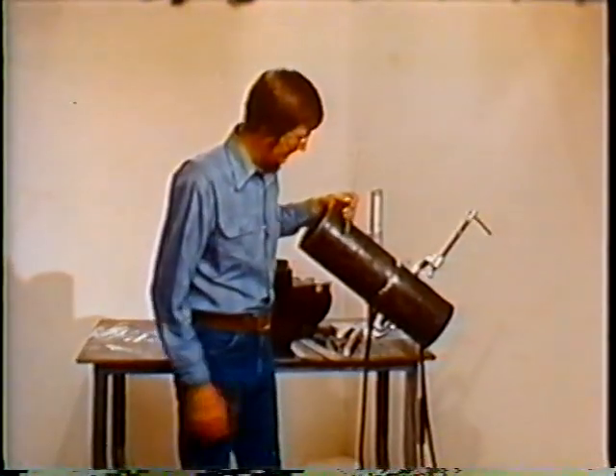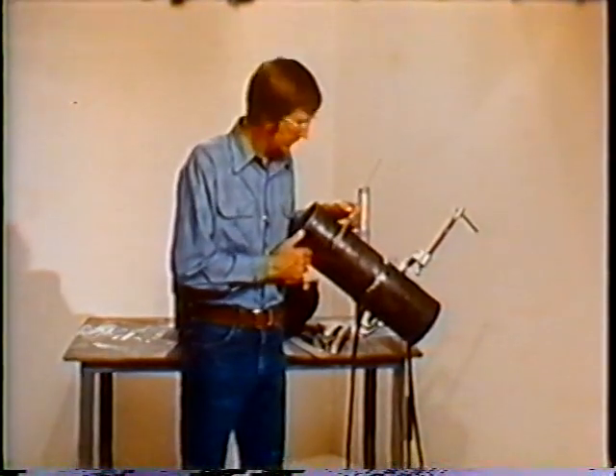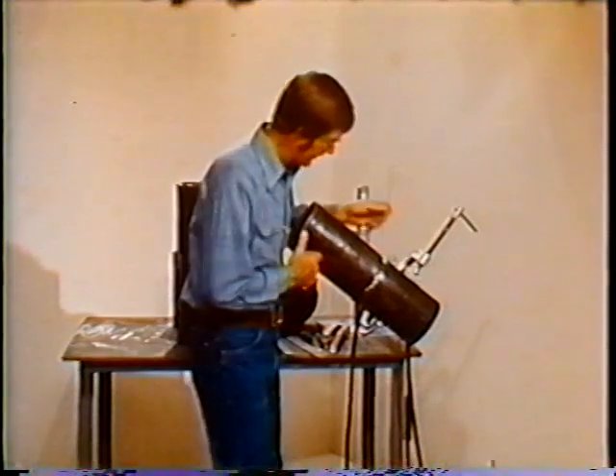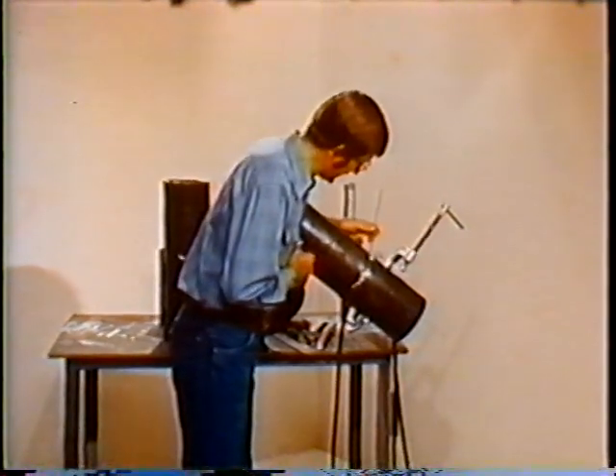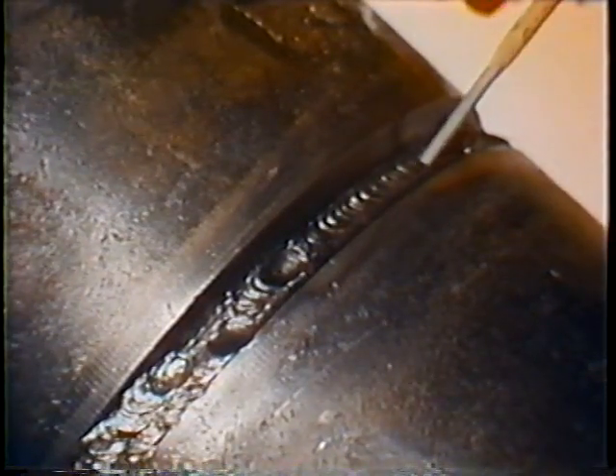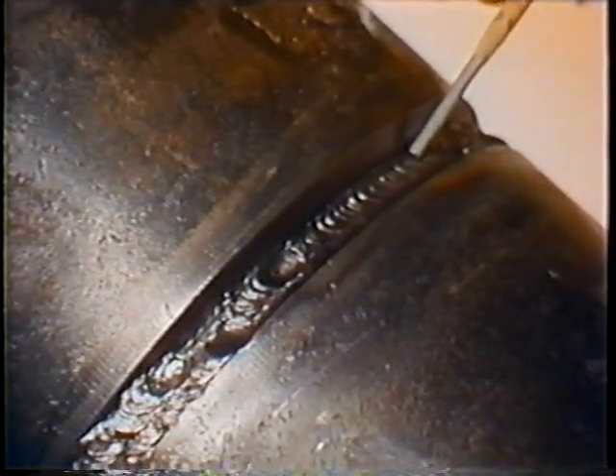We have a specimen in the 6G position now made like the one you just saw in the demonstration with a staggered bead sequence that we can talk about. First of all, of course, there's the root pass here that was made now with the vertical up technique, remember, so you'll notice the ripples are a little coarser than what we experienced on the previous sample. And you'll notice that it's smooth and well cleaned and is properly fused in on both sides.